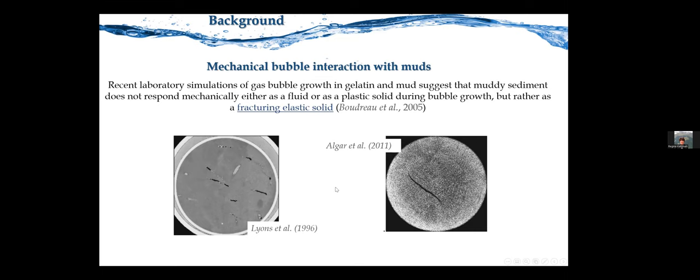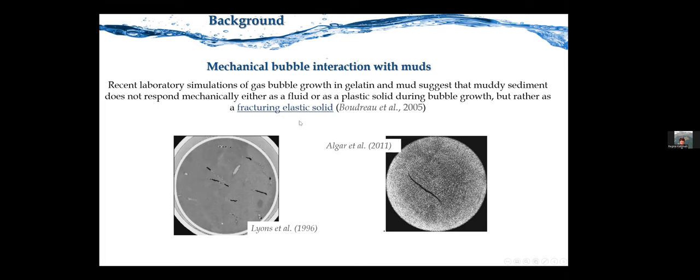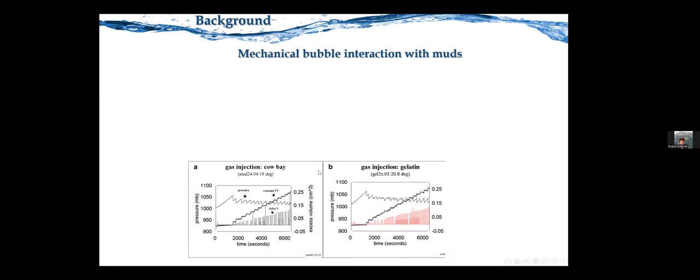So from this and other laboratory simulations of bubble growth in muds and in gelatin, it could be inferred that muddy sediments do not respond mechanically, either as a fluid or as a plastic solid, to bubble growth, but rather as fracturing elastic solids, despite the fact that muds are very soft materials. So in order to confirm this hypothesis, that muds in their relation to the bubbles are fracturing elastic solids rather than a plastic solid, for instance, or fluids, okay,